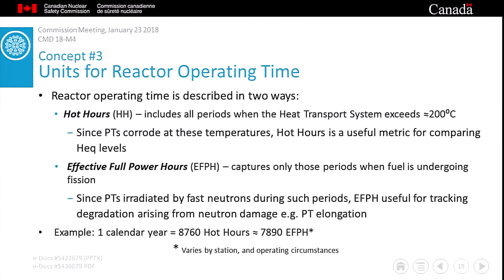Finally, I'd like to distinguish between two units of reactor operating time that Bruce and Pickering representatives may use during the Part 1 relicensing hearings. Hot hours, which is the cumulative time the primary heat transport system is above about 200 degrees C, and effective full power hours, which is the fraction of the hot hours when the reactor is at full power. Each of these units has a slightly different application. To illustrate the difference between the units, the slide indicates the number of hot hours in a calendar year and the corresponding effective full power hours for a typical Canadian reactor.